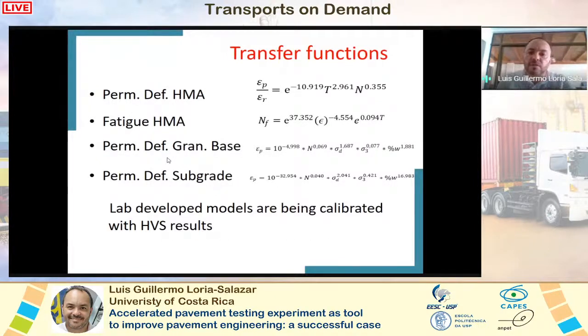And you can see over there the various transfer functions we developed for fatigue, for permanent deformation of the hot mix asphalt, for permanent deformation of the granular base, and permanent deformation of the subgrade. In the case of the granular base, you can see the various variables: the deviatoric stress, the confinement stress, and also the percent of water, the humidity of the material at the moment when you are working.